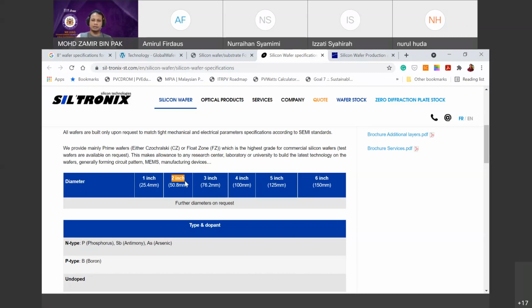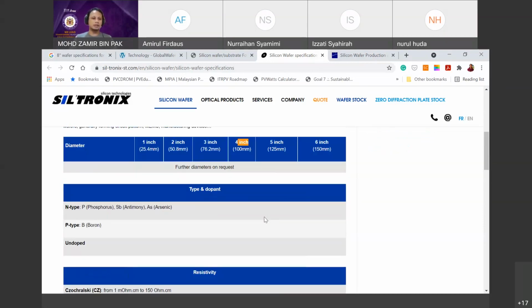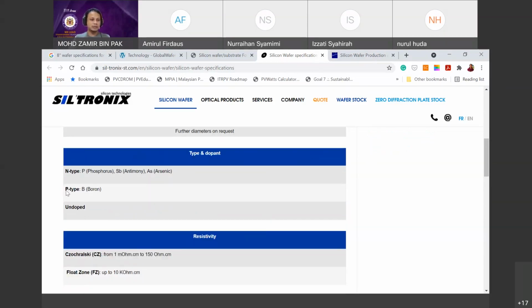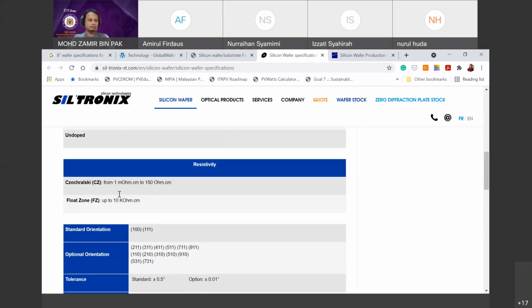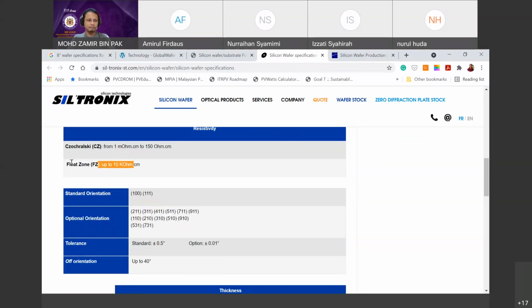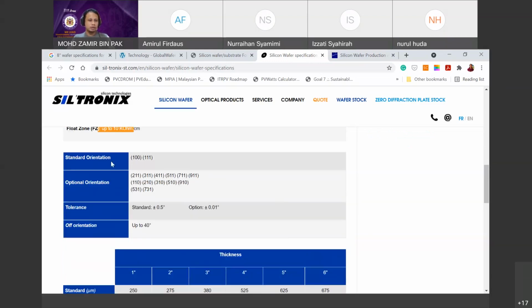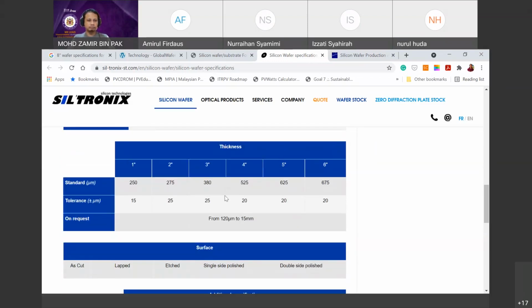So that means the ingot process and the crucible will be very, very small. Okay. So 3 inch dia ada ingot growth, 4 inch, 5 inch, 6 inch. Okay. So typically more towards lab application, I believe, because they don't have anything above 6 inch. So N-type, phosphorus, antimony, arsenic as the dopants, and then P-type is usually boron. Okay. So Czochralski or float zone. So it depends on the either growth process do you want. Orientation, different are provided. Okay, tolerance of the orientation. Okay, thickness. You can see standard thickness.